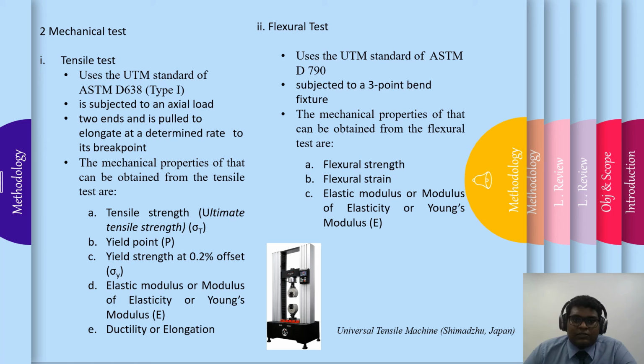Next, the flexural test. The flexural test method measures the behavior of material in which specimens of a standard shape and dimension are prepared according to ASTM D790. The specimens are subjected to a simple bending load with a 3-point bend fixture, which will test the specimen of the 3D printed part. The 3-point bending flexural test provides the value of modulus of elasticity in bending, flexural stress, flexural strain, and the flexural stress and strain response of the material.